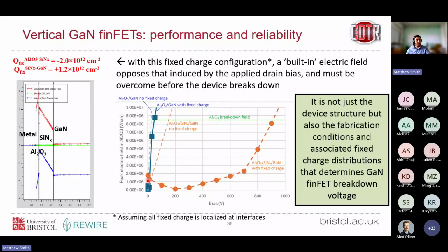So this is our characteristic, this orange dashed line here. Without the fixed charge, we can see it's breaking down around 100 volts. But when we get this fixed charge configuration here, it's fighting against our electric field initially, and then once it's done that, we're able to achieve this kind of 900, 1000 volt breakdown voltage. So, an interesting result. It's not just the device structure, but also the fabrication conditions and the fixed charge distributions that determine the breakdown voltages in these devices.